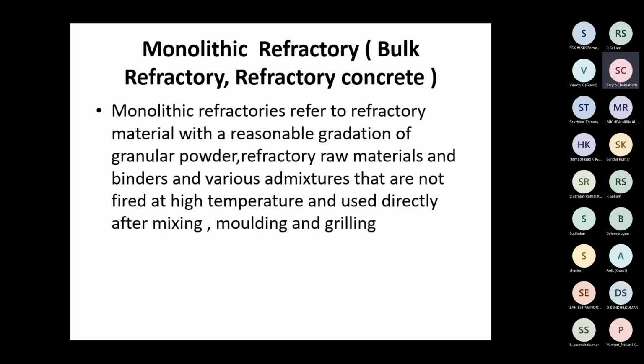Monolithic refractory is a bulk refractory, like concrete, because in the industry a lot of refractories are unformed. Monolithic refractories refer to refractory materials with a reasonable gradation of granular powder, refractory raw materials, binders, and various admixtures that are not fired at high temperature and are used directly after mixing, molding, and curing. It is not fired, but cured, like we grill our sandwich before eating. Then who does the firing? The furnace does the firing. The site does the firing itself. It gets its strength by firing inside the process, not before that.